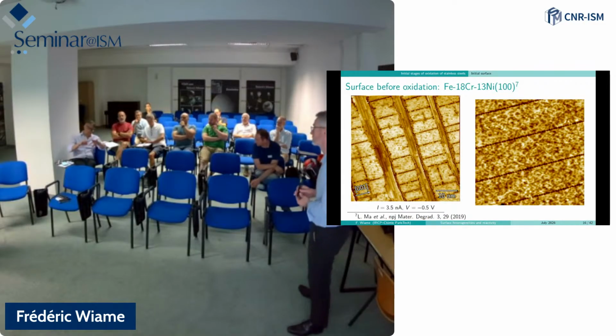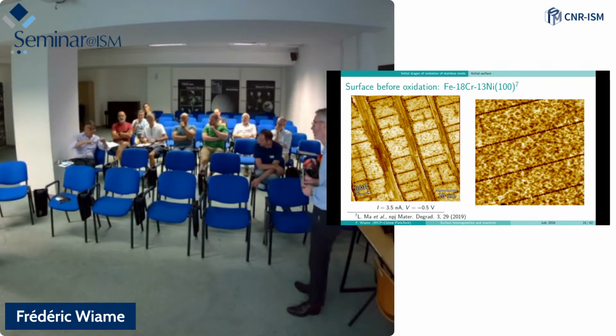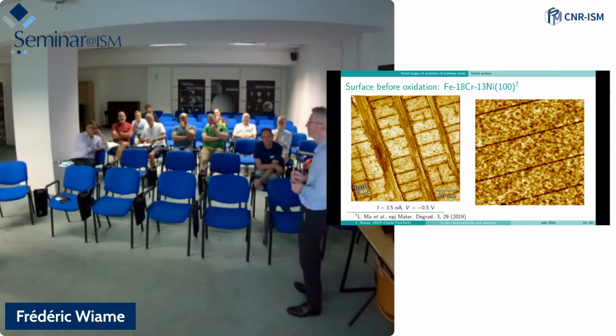So what the question was: you showed that nevertheless, you have chromium oxide, and you still form these pillars of iron oxide. So when you put chromium oxide from the very beginning, can you form these pillars or not? It depends. If you are depositing chromium oxide directly on the surface, it will probably be the same kind of problem of heterogeneity at the surface. You change the mechanical properties also.